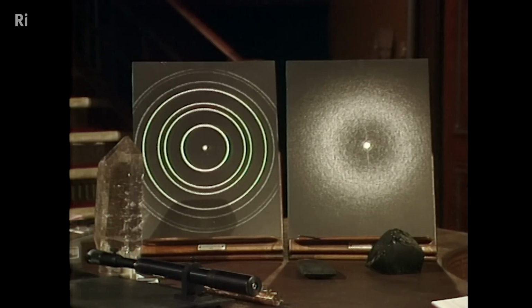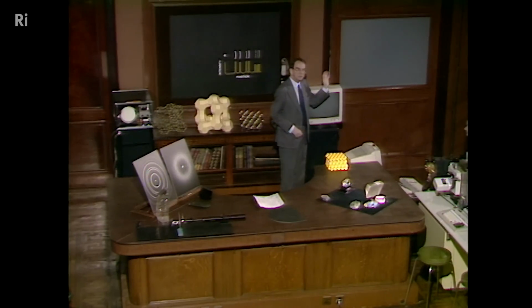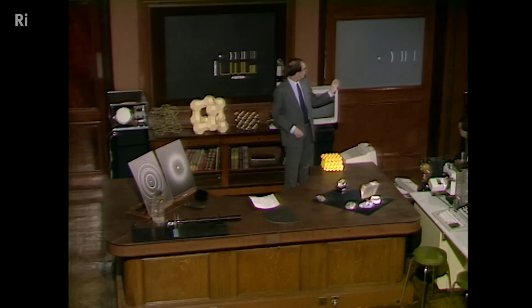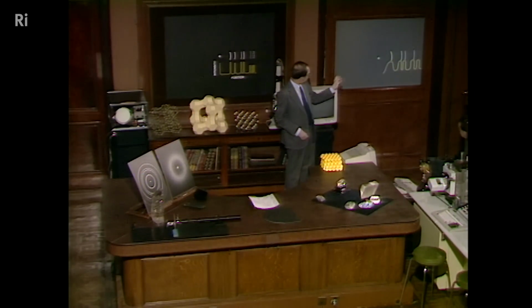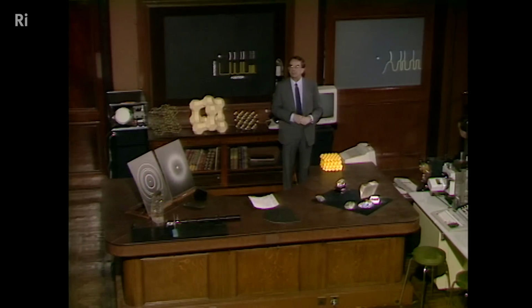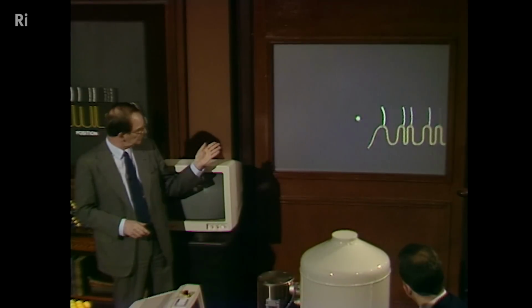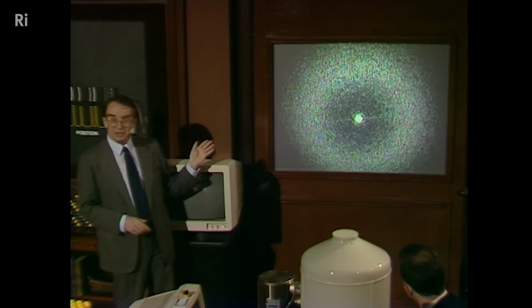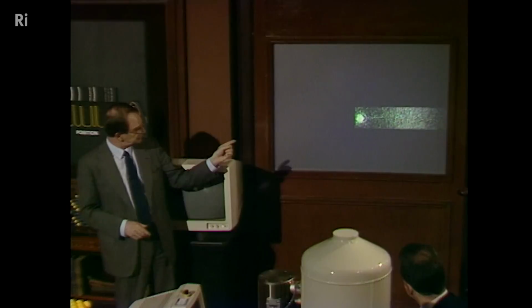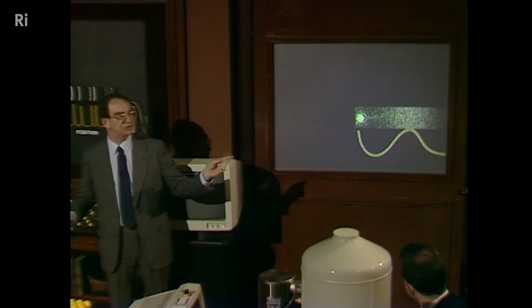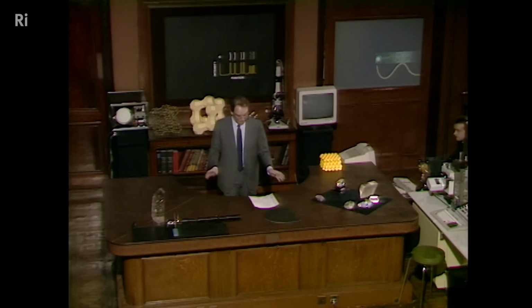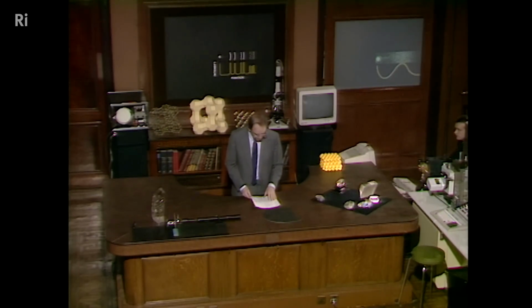In fact, there's an animation that we've got here for you. Watch this very carefully. Shortly on this screen, we show you quartz again. We show a part of the quartz, and now we show you the characteristic diffraction pattern. Let's compare that with what comes next. Next, we're going to show obsidian, which is a very diffuse pattern. That's the diffraction pattern, one broad single line. So that's how we know the difference between a crystalline and a non-crystalline material.